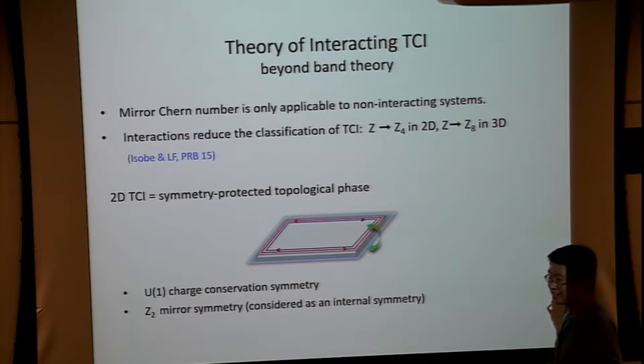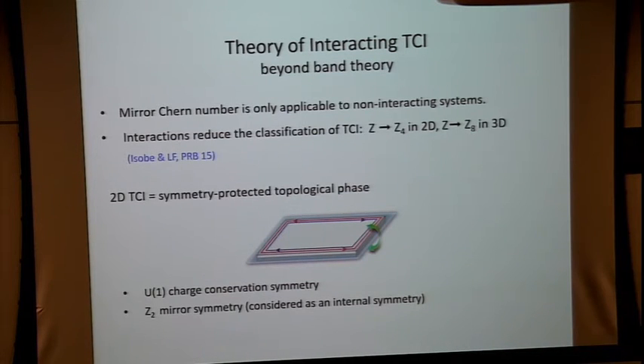Somebody was telling me yesterday that no lecturer has explained this kind of phenomenon, interaction-enabled reduction. The first pioneering work was by Alexei Kitaev in the case of one-dimensional topological superconductors in the BDI class. There, the topological index is an integer within the band theory framework, but with interaction, it reduces from integer to Z8. In other words, when you have 8 Majorana zero modes at the end of a one-dimensional topological superconductor, they can open up a gap.